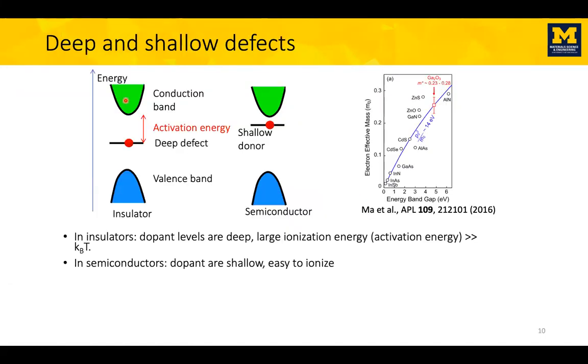And I'd like to talk a little bit about the dopants first, the doping. And I want to make a contrast between deep and shallow dopants. So what makes semiconductors semiconduct compared to insulators? Like, why is silicon different than wood? The difference is that if you take a foreign impurity atom and put it in silicon, like a phosphorus ion or a boron ion, it will give you shallow dopants, meaning they will give a state in the band gap that is only a few milli electron volts from the band edges. So at room temperature, those electrons would leave the localized states, go to the band, and conduct electricity.